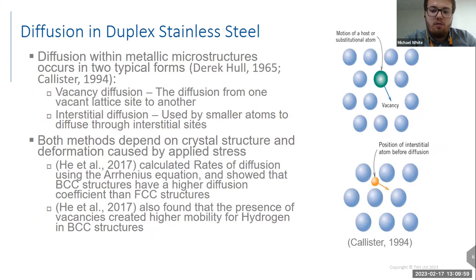Vacancy and interstitial diffusion are the most common methods of diffusion in metallic structures, shown in the images on the right, with vacancy diffusion in the top image and interstitial diffusion in the bottom image. As shown by experiments conducted for the International Journal of Hydrogen Energy, rate of diffusion can be calculated using Arrhenius equations. During the experiments they calculated diffusion rate for different crystal structures and showed that body-centered cubic structures experience significantly higher rates of diffusion than face-centered cubic structures, which is significantly important because face-centered cubic and body-centered cubic structures make up the duplex structure of duplex stainless steel, which represents the relevance of crystal structure within hydrogen transport or containment.